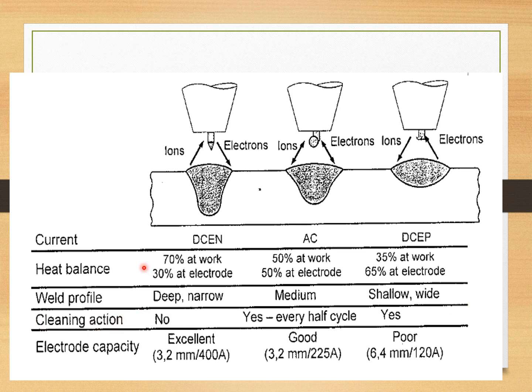Cleaning action: for DCEN is not required. For alternating current, yes, every half cycle. Direct current electrode positive always needs cleaning. Electrode capacity: DCEN is excellent, 3.2 mm at 400 ampere. Alternating current is good, 3.2 mm, 225 ampere. DCEP is poor, 6.4 mm at 120 ampere.